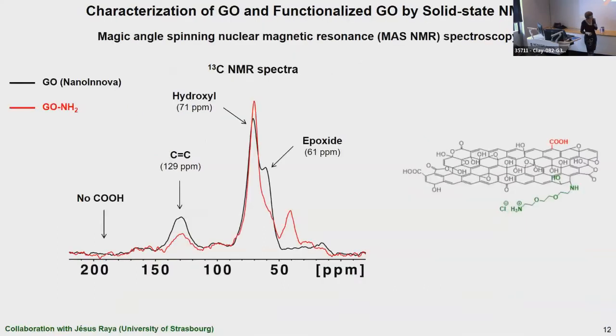We characterized the graphene oxide and the functionalized graphene oxide by solid state NMR, in particular using magic angle spinning NMR. So in black, you can see the carbon-13 NMR spectrum of the starting graphene oxide. There are three main peaks. This one at around 60 ppm assigned to the epoxides. This one at around 70 ppm for the hydroxyls, and the carbon-carbon double bonds here at around 130 ppm.